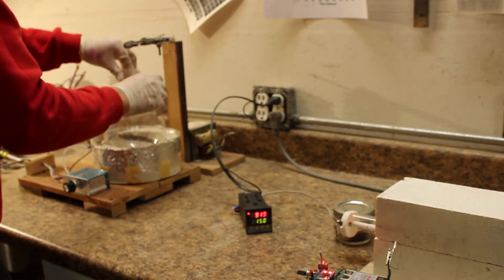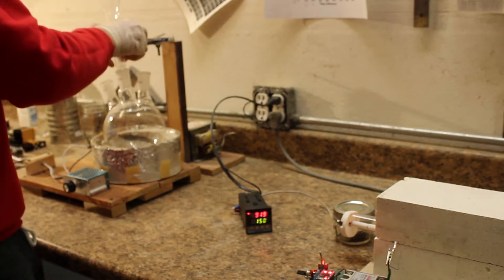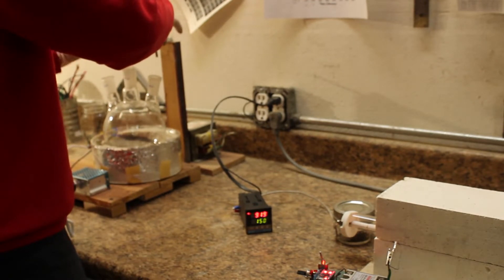This however is a terrible way of doing it as the steam condenses in our tubing and shoots large amounts of water directly into our furnace, which boils quite violently. In the future we will make some improvements on this method.